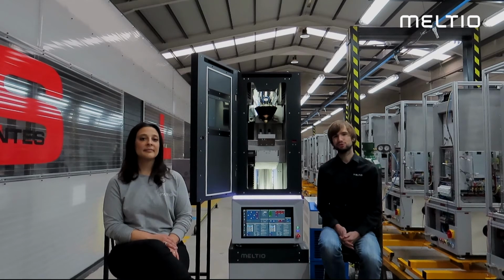And number 3, process control. This is a closed-loop system that detects if there's a lack of deposition within a component, and then it adjusts the laser power and material feed rate automatically to compensate and build the part right back up to the nominal height. This system is very useful, especially when working with new materials or new parameter sets, because it means that many parts that would have failed otherwise can be recovered and finished perfectly. In case an unfixable error is detected, the system will stop automatically and alert the user.